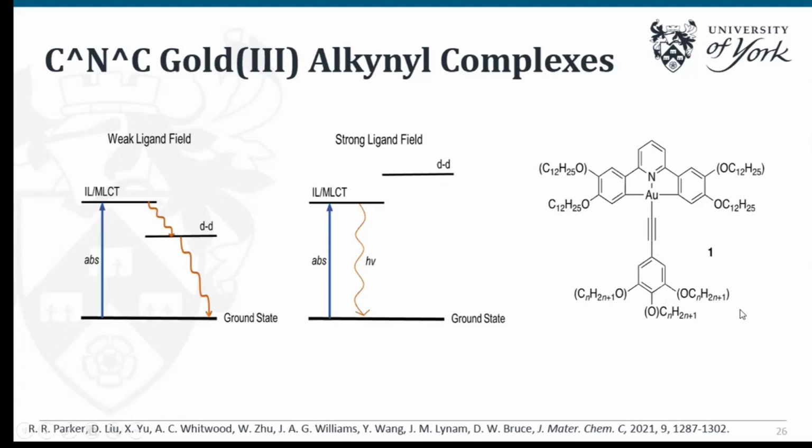One of my supervisor's previous PhD students, Dr. Rachel Parker, did a lot of work on this type of gold complex. She discovered that when you put these long chains on them in the 4 position and the 3,4 positions, depending on the length and number of chains on this phenylacetylene ligand, you could get columnar liquid crystal phases. She also showed that they could be used in prototype OLED devices, giving both yellow and green emission, in a collaboration that the group has with a group over in China.